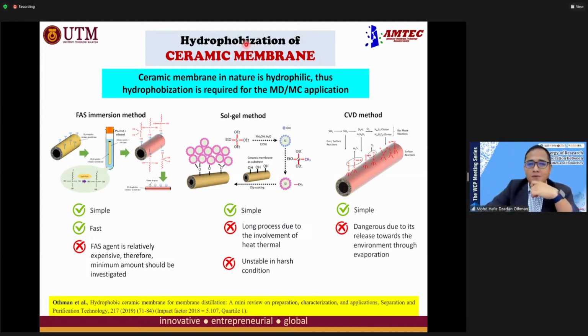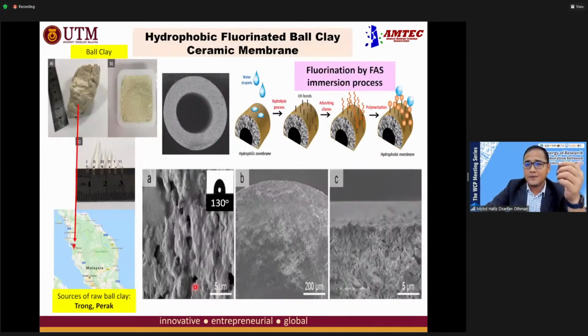For this hydrophobic membrane application, we use a ball-clay membrane that we also obtained from one of the states in Malaysia, in Perak. We crush the ball clay, we produce it into a hollow fiber membrane, and after that we do some hydrophobization on the membrane in order to obtain a super hydrophobic membrane. Just imagine, from a 10 degree contact angle, it can become a 130 degree contact angle by using this FAS immersion. So we subject this membrane to membrane distillation.